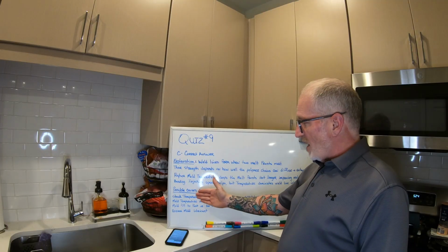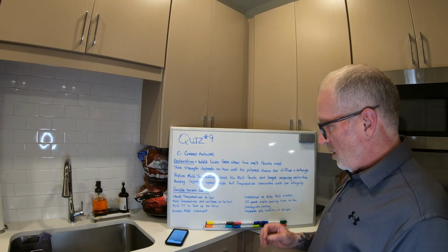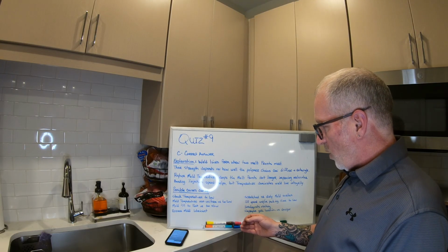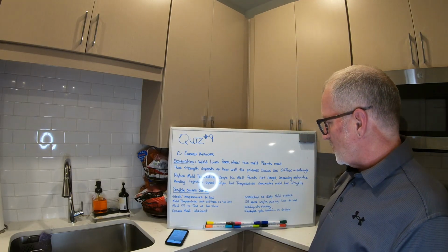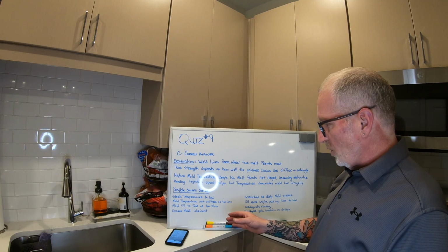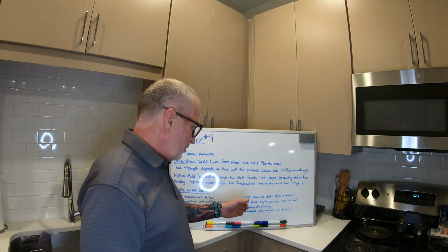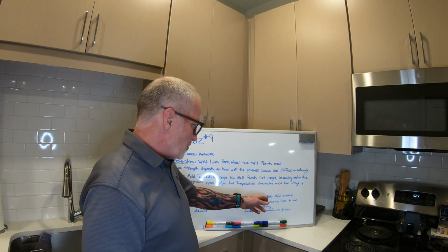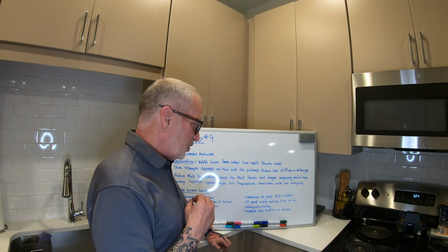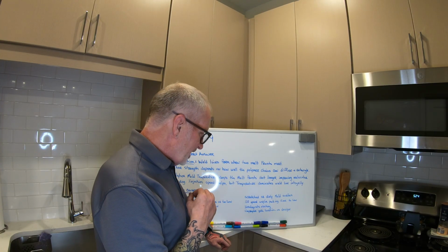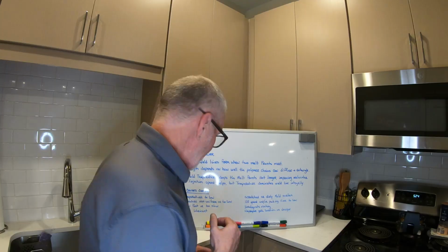This is possible causes that can happen. So, stock temperature too low, mold temperature non-uniform or too low, mold fill too fast or too slow, excessive mold lubricant. So if you spray your molds down too much with lubricant, that can actually cause it. Scratched or dirty mold surface, fill speed and/or pack time too low, inaccurate venting, and then improper gate location and design. So think about that.